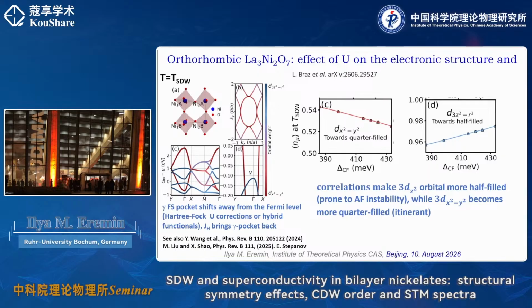At the same time, if you look into the occupation of the dx square minus y square, you see that this simple-minded Hartree-Fock correction already tells you that it wants to become just quarter filled. So it wants to become more itinerant. So even at this level. Again, let me tell you that since there are two parameters, U and J, if you do not do just simple-minded Hartree-Fock but something more advanced like Trilex, which we also did, the results are a bit different. But I just wanted to tell you that even with this itinerant perspective, you agree that the dz square is more correlated than the dx square minus y square.